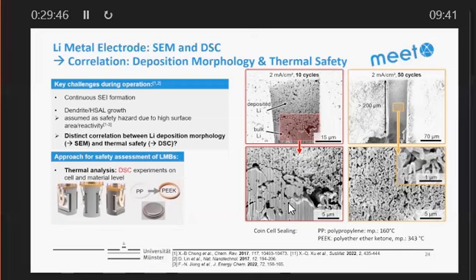And we see that the SEMs give us, let's say, very similar deposits, but you see also that if you look here at the enlargement, here we still have a lot of bulk lithium because it's only a few cycles, and here all the lithium is already used up because we have 50 cycles and we have more high surface area lithium.